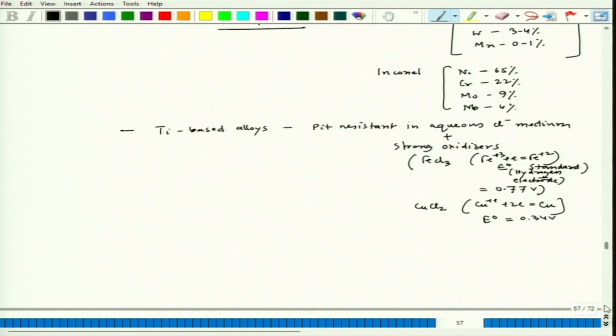And now you could see that wherever the pitting ability is very high, and we have also seen in terms of corrosiveness as well as corrosion resistance plot, the more aggressive the medium, the higher would be the restrictiveness to select materials. And of course, the cost part would also come in. As we see in comparison to general corrosion prevention, for pitting corrosion prevention, because it is a localized pattern, we need to go for stainless steel, which is also high alloy steel, nickel based alloys, which contain a lot of molybdenum, Hastelloy, Inconel, or titanium based alloys, which is also a very costly alloy system.